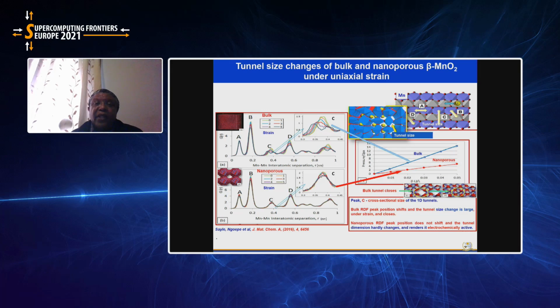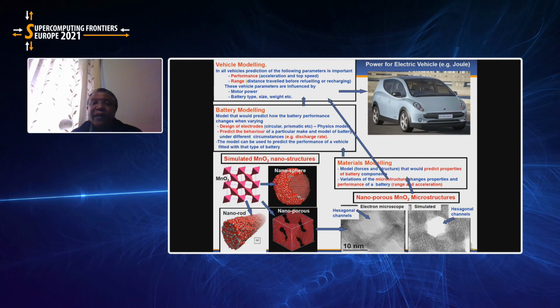This picture here just shows the pores through which lithium, which is in yellow, can move. It is represented by this number C, and that number C corresponds to this peak C. You can see that as you apply pressure, when you put lithium into this bulk structure, that peak shifts significantly. When you do the nanoporous structure, that peak doesn't shift. This means that the nanoporous structure is very good and ideal for taking lithium in and out, and we can charge and discharge the system without the structure being destroyed.